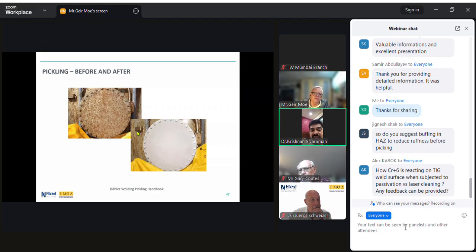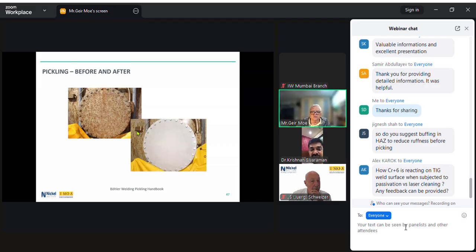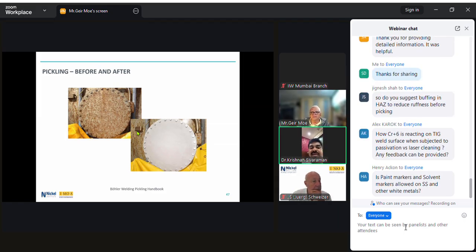Yeah, there are some similar questions. I see one here on laser cleaning as a substitute for pickling, to get the same effect. Well, you can use laser cleaning to remove heat tint, but to me it's the equivalent of blasting. There's no way to ensure that you remove the chromium depleted layer. You could certainly use it, but it doesn't really replace pickling, because you can't ensure that you've removed the chromium depleted layer.